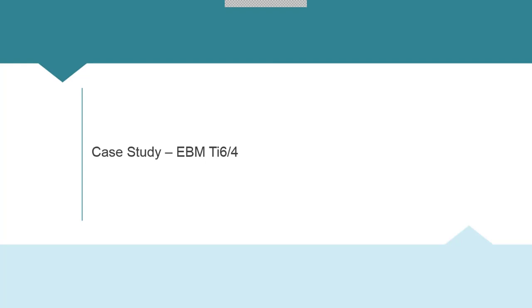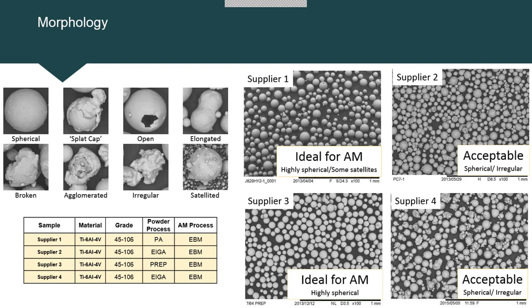So I've got a few slides that I can run through reasonably quickly that go into a case study looking at 4 suppliers of titanium 6-4, which was used for an electron beam melting application. So nominal size would be 45 to 106 microns. So the first thing we want to look at is morphology. So we can do this in a number of ways. On the slide now is showing you a comparison of SEM images of the 4 suppliers.